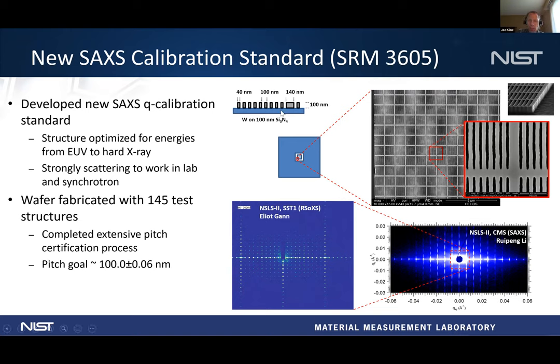And superimposed on top of the 100 nanometer pattern is a 1 micron square pattern. And by having that super lattice structure, you can see you get a very complicated two-dimensional scattering pattern. And so it makes it very nice for being able to calibrate the detector. And if you zoom way in with something like soft X-rays, where you have really high resolution, you can see the little dots that are coming from the 1 micron square array. And so it's almost ready for full production. We had a wafer fabricated with 145 test structures, and we just recently completed the pitch certification process on it. And it's pretty close to 100 nanometers and pretty uniform across the whole wafer.